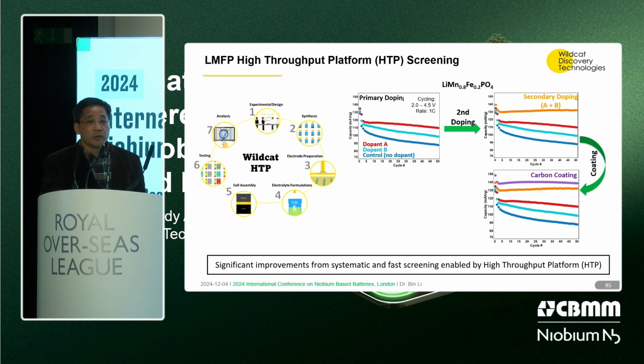For these materials, we know the conductivity is not good. The carbon coating is very important. So we use our high throughput to do the carbon coating. That's including different types of carbon coating conditions, those variables. Then you will see we can make further improvement, especially for initial capacity. You get almost 150 milliamp hour per gram and much better cycle life. Then so this is another round.